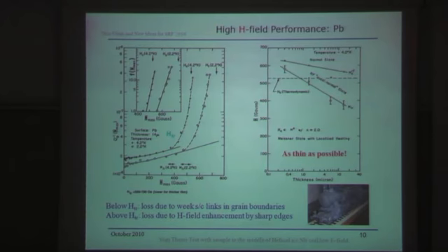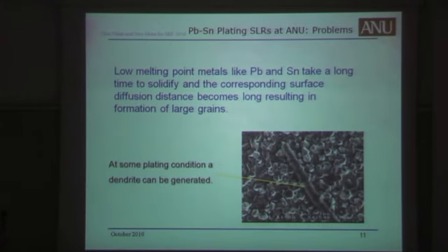Okay, so what problems do we have at ANU? Very similar structure. There is not much control in electroplating of superconducting layers, so it results in the formation of relatively large grains. When I try to plate a few microns, 10 microns, usually grains are proportional to the thickness of the layer, and you don't have much control. And quite often you can also end up growing these beautiful structures, dendrites, and so on.